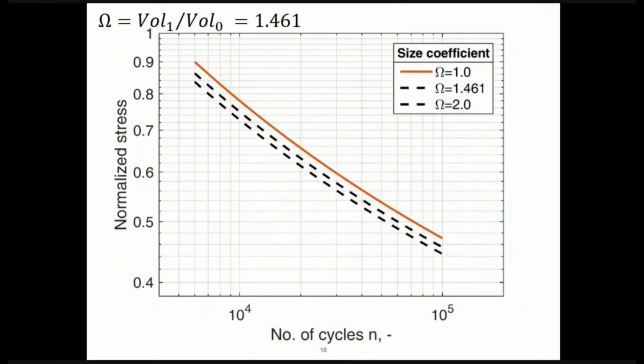So in this case, the omega value, so the volume, is 1, because here you can see the equation for the omega. It's basically the current volume divided by the calibration specimen volume. So in this case, it's just 1. The middle dashed line is the test results we use. So the omega here was 1.461, so a 46% bigger volume of the specimen, and as we should predict, the fatigue life was a bit lower.